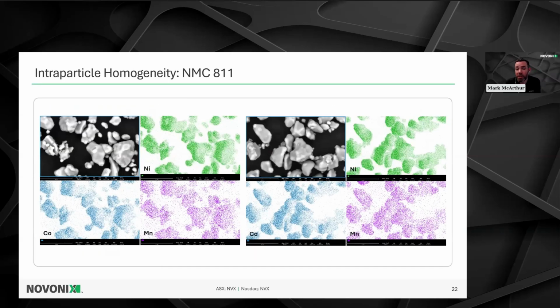The intraparticle homogeneity of these materials for at least 2 different spots were measured by SEM and EDX. Rather than doing single point measurements over 10 or so particles, what is done here is a map of the characteristic signal from each of the elements, whether that's nickel, cobalt, or manganese. And we do not see any localized islanding, no localized bright spots of manganese in particular in this mix. So that indicates to us that the homogeneity of the metals in this powder is quite good.